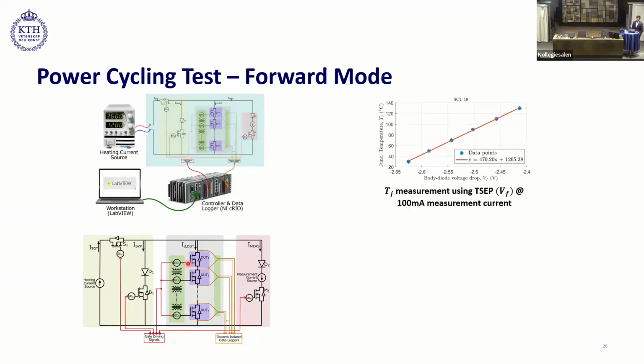For the temperature measurement, we used a temperature-sensitive electrical parameter, body diode forward voltage, which is measured at 100 milliamps measurement current. Here, we are looking at the calibration data of this TSEP. So we see that the body diode forward voltage changes with junction temperature. We feed this calibrated equation directly into the test bench, and during the cooling time, this gives us the junction temperature.